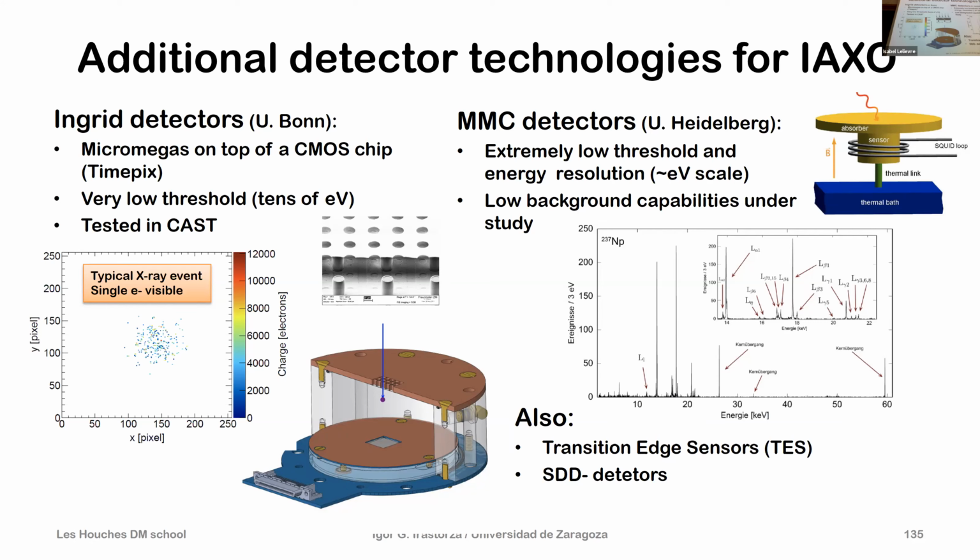But this is an onion layer strategy. You choose a very clean material close to the detector, and typically the closest material is not lead but copper. The body of the chamber is made of very clean copper. Then you can start putting very clean lead, and usually whatever remaining radioactivity the lead has is blocked by the copper.